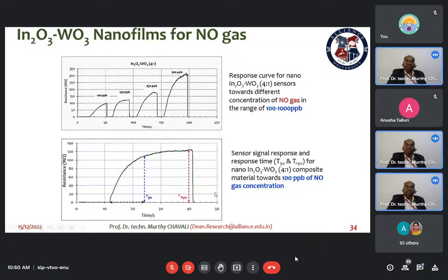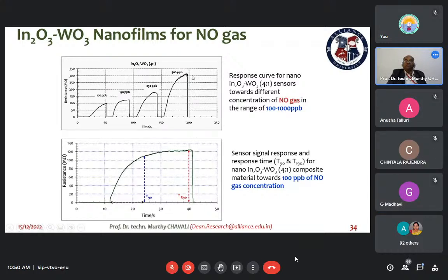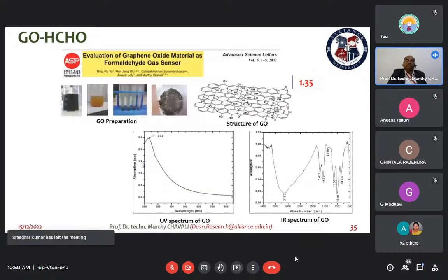So T90 and TR90 are going to be highly effective, and we were able to detect something close to 25 ppb, parts per billion level, not even ppm, but ppb, at room temperature using this particular material. And then we wanted to take it to the next level, going from gas into liquid matrix, but the results are not that sensitive compared to the gas and gas matrix. So we are still working on that, so that we will be crossing the ppm barrier to the ppb barrier.